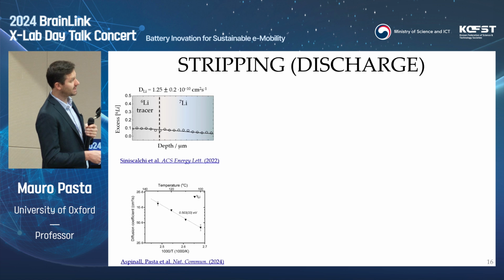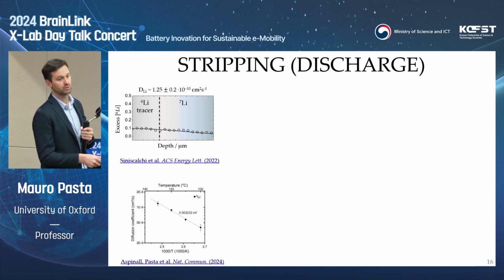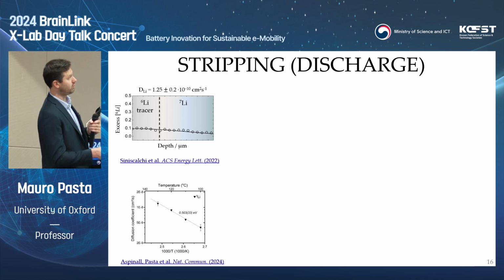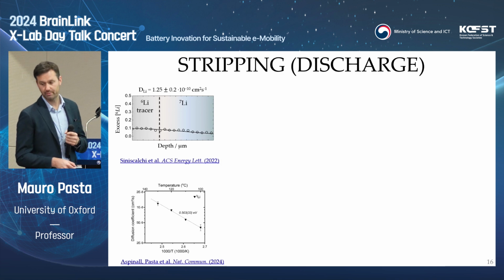So if you put in contact a lithium-6 foil with lithium-7, and you then cross-section it, and you use the lithium-6 as a tracer, you can, if you record the time, visualize this concentration gradient, model it with Fick's law, and get the diffusivity out. And we get a value of 1.25 × 10^-10 centimeters squared per second.